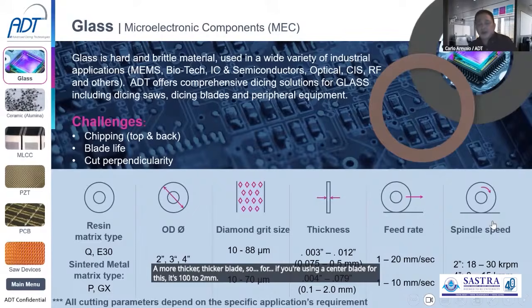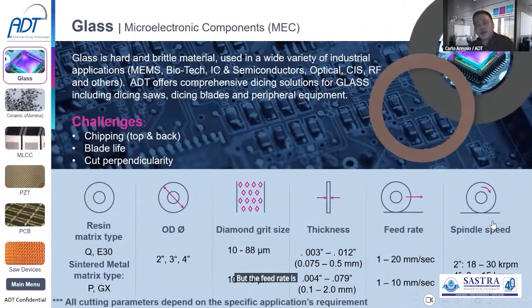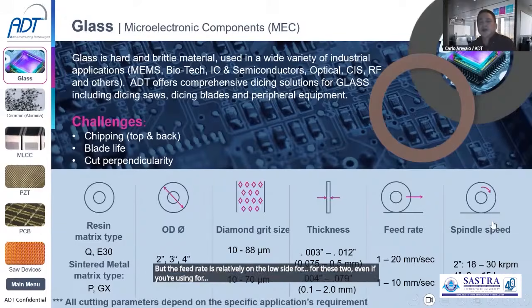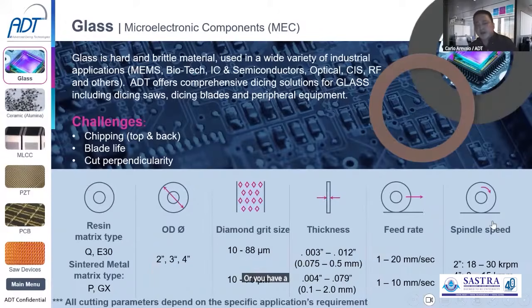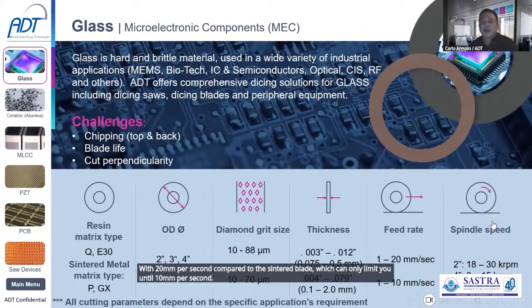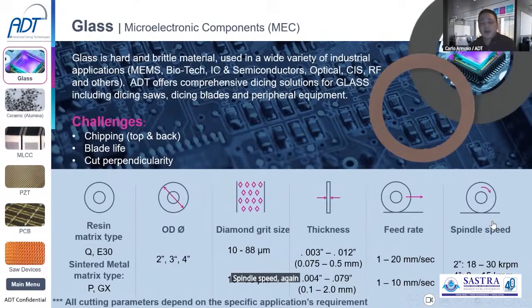But the feed rate is relatively on the low side for these two types of blades. You have a slightly faster feed rate if you're cutting with a resin blade, at 20 mm per second, compared to the sintered blade, which can only go up to 10 mm per second. Spindle speed, again, would be dependent on the blade size or the equipment that you're using. So this is also something that needs to be developed.